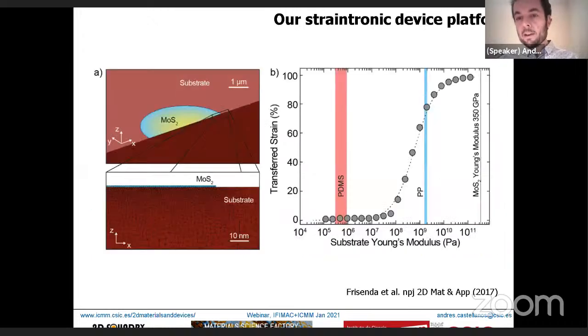One take-home message is that the technique works quite well, but you have to be very careful with the substrate you use. For instance, polydimethyl siloxane has a huge thermal expansion, but its young modulus is very small - it's quite floppy material. The amount of strain you can transfer from the polymer substrate to your flake depends on the substrate's young modulus, so you need a substrate with both large young modulus and large thermal expansion. Polypropylene or polycarbonate are quite suitable materials, but polydimethyl siloxane is really bad for this application.